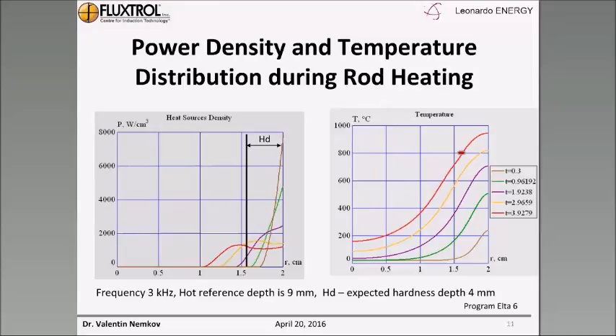Here, at this point, we have a non-magnetic transformation, a non-magnetic layer of material on the surface, and the curve of power distribution changes dramatically. From here then to here, the non-magnetic layer with temperature above the Curie point gets thicker. And the final ideal distribution for surface hardening is this red one.